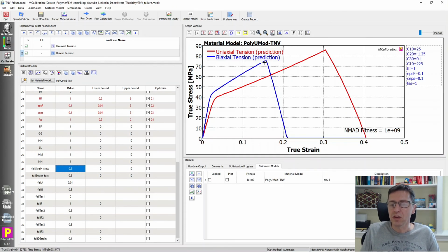In the biaxial test, the failure strain is different because of the nature of the strain state. So that is not due to triaxiality, that's just simply because of the strain state dependence of this material failure condition. If we want to change the triaxiality condition here and the influence of that, we can do that using the factors here, F1, F2, and F3. And the way that works is that for each triaxiality value, this is stress triaxiality of 0, the factor is 1.